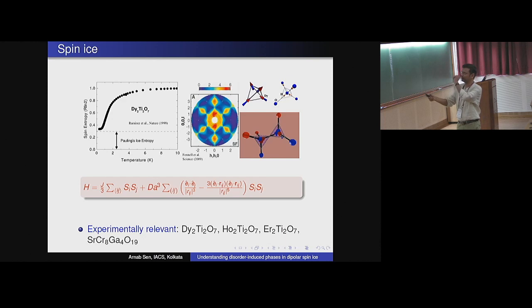First, the spin should be thought of as Ising degrees of freedom. But these Ising degrees of freedom here do not have, if you wish, a uniaxial nature. So imagine that you have a tetrahedron here, and there's the centroid of the tetrahedron. So you just draw lines out of the centroid. Then these spins basically point in or out of these lines, okay? But they are, of course, Ising degrees of freedom because they have just these two directions to point in, right? So in or out, okay?